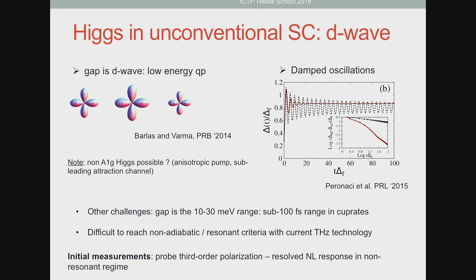And in the dotted line, this is the case of S-wave. And in the red line, this is D-wave, and you see immediately that the damping in the case of D-wave is, as expected, much faster than in the case of the S-wave superconductor. So that's one challenge. In terms of transient dynamics, you will expect this two-delta oscillation to be much more short-lived. Now, there are other challenges, but they are more technical.